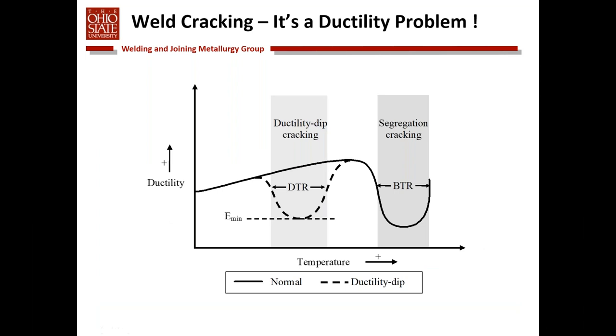So if we think about weld cracking, it's really a ductility issue, right? Why does a weld crack? A weld cracks because you impose a strain on it, normally during the solidification or cooling process of the weld. And if that strain exceeds the inherent ductility of the material, it cracks. And so there's two approaches. We can try to increase the ductility of the material, or we can try to decrease the strain that's applied during the welding process.